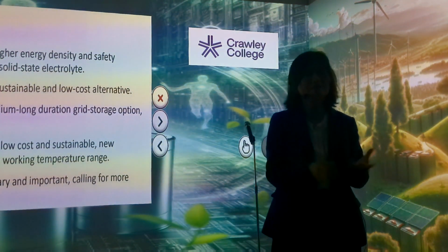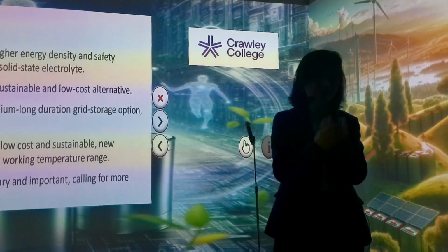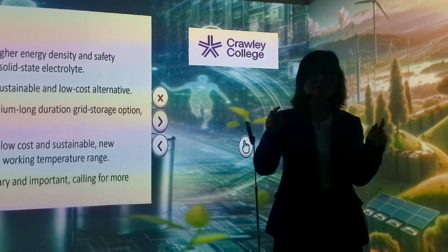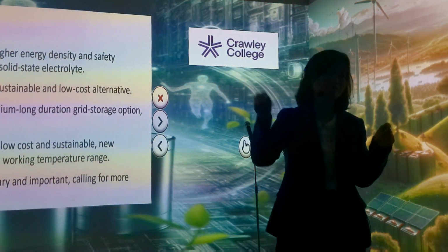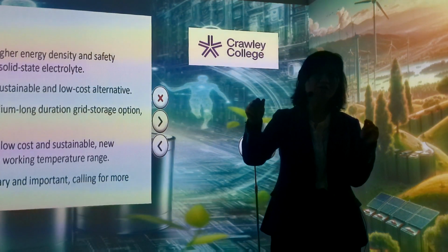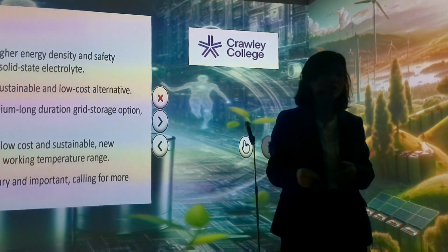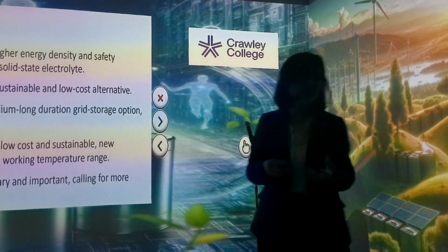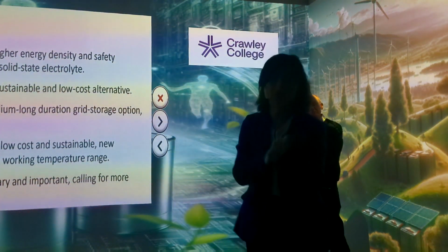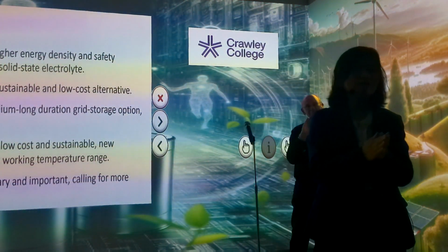And once you have oxygen in your batteries, it can ignite and react with the electrolyte, because you have organic solvent electrolyte. They can easily react with oxygen. And plus, in that charge and discharge process, because there is a lot going on when you move lithium out and in the material, you have some resistances that the system needs to overcome. And those resistances convert into thermal energy. So you have a temperature increase.